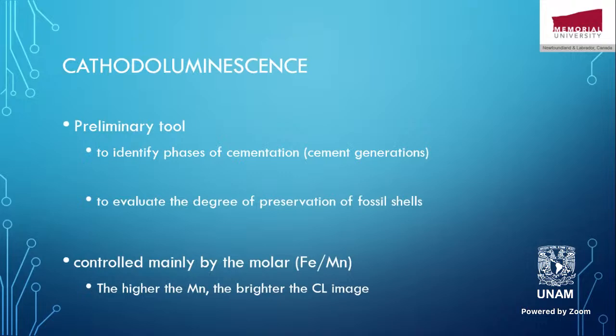We see luminescence patterns in those carbonates like zoning, concentric zoning, and this helps us to identify the different generations of cements under the microscope. When we look at those cements under a petrographic microscope, under plane polarized light or even crossed nicols, we see all the cements looking like each other. If they are all blocky cements, they look like each other. But when we put them under cathode luminescence, we start to see probably two generations of those cements, not one generation, depending on the luminescence of those cements.